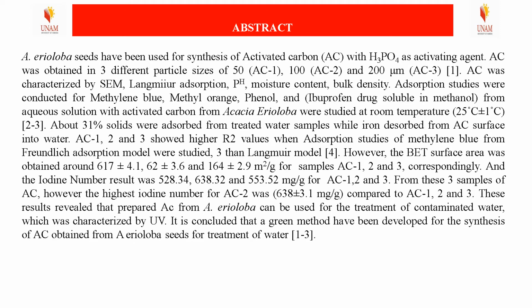From these three samples of AC, the highest iodine number was for AC2, 638 plus minus 3.1, compared to AC1 and AC3.